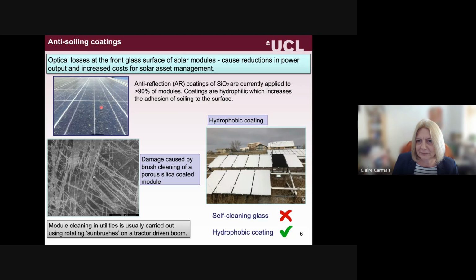There's an anti-reflective coating of silica on the top surface, so they're applied to about 90% of these modules. Now, silica, to get it anti-reflective, it has to be quite porous silica. They're hydrophilic, and the problem is because it's porous, when you go through the action of cleaning, and the cleaning of the utilities is largely done using very large sun brushes that are on tractors, you can see that it ends up causing damage to the porous silica. And also the silica being hydrophilic increases the adhesion of the soiling to the surface.